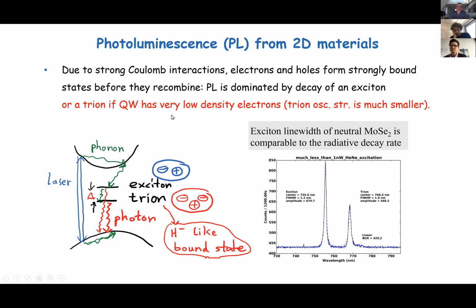Now, if there are electrons in the system, then there is another possibility. The exciton can correlate its motion with an electron and form a molecule, which is an analog of the H- molecule. And this is what we refer to as the trion. And even though its oscillator strength is small in the low electron density limit, one would nevertheless see it in photoluminescence because it does provide the lowest energy state for the optical excitations.